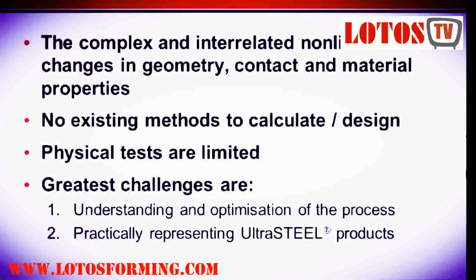So by applying the dimple on the section, for the whole thickness and the whole section, we are applying the cold work on the section, which can significantly improve the strength of the material and the end product. But we face some design challenges.